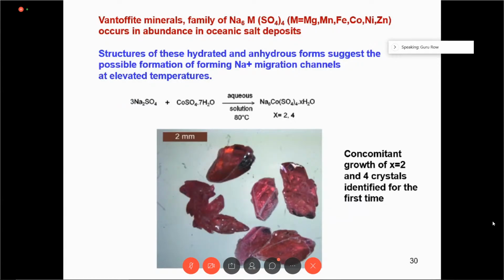So the structure of these hydrated and anhydrous forms suggests the possible formation of sodium ion migration channels, just like we discussed before. And so if we take the sodium sulfate and cobalt sulfate with excess water in the aqueous solution at 80 degrees, we can crystallize this mineral.